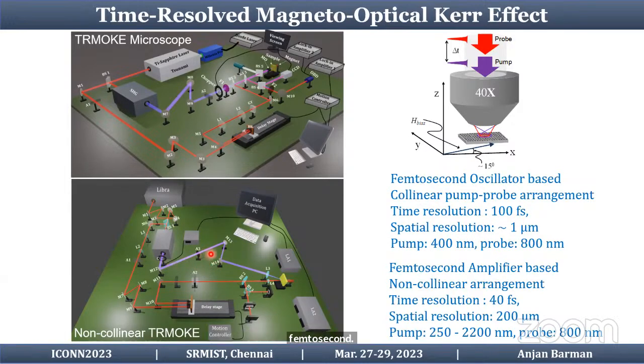This is another setup, which is based on a femtosecond amplifier system, which is Libra in this case. And here also we do this two-color pump-probe experiment, but here we do not do the collinear measurement. It's a non-collinear measurement. And here pump and probe are not tightly focused, so the spatial resolution is only 200 micrometers. That's not a problem because we measure with a better time resolution of 40 femtoseconds and a pump wavelength variation from 250 to 2200 nanometers, which gives us the time-resolved spectroscopy as well.